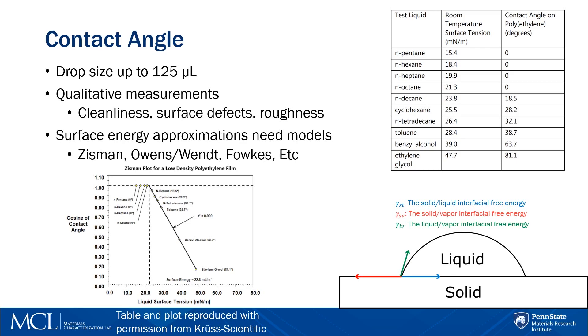If you end up having polar contributions on your surface, you have to use a model like Owens, Wendt, Fowkes, or there are many others. The Zisman model states that the surface energy of a solid is equal to the surface tension of the liquid that is just barely wetting the surface completely, corresponding to a contact angle of zero. For this example, we stop witnessing complete wetting at 23.8 mN/m, which is the value for n-decane, putting the surface energy somewhere between 21.3 mN/m for octane and 23.8 mN/m for decane.